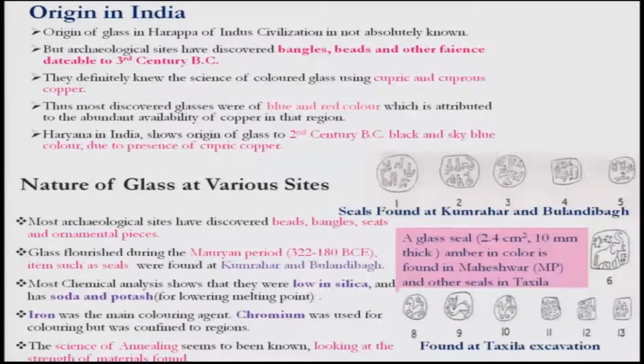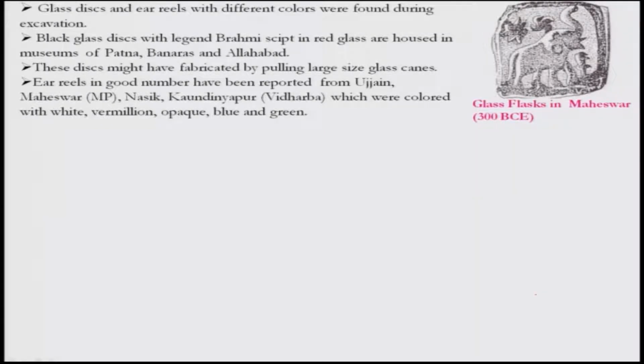Here I am showing you a glass seal of 2.4 centimeter square and 10 mm thick, which was obtained in Maheshwar, MP, along with other seals in Taxila. This one has an amber color. Several seals were also obtained in Taxila during excavation, with different motifs. From this one can conclude that the science of annealing was known to the ancient glass making people, because the strength of this glass was quite good, which would not be possible without annealing. That is a glass seal obtained in Maheshwar, dated to 300 BC.